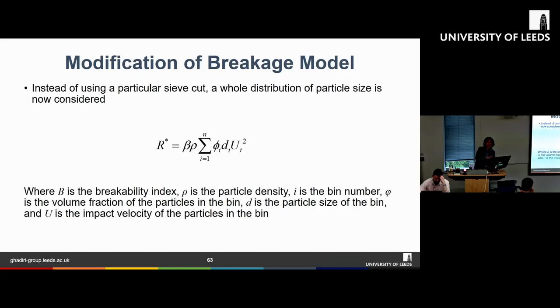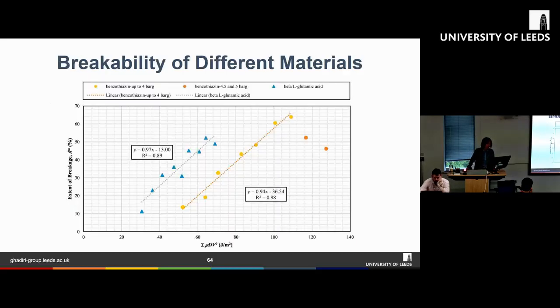Using Ghadiri and Ning's model, we can apply this method to describe the breakage of acicular crystals. Here we made a small change to the model: instead of using one single narrow slit class of crystal, we use the full distributions of the particles and then do the impact test. As a result, we need to give weightage to the different particle slit sizes and then fit them into this model. Having done that, we come to this very nice correlation here.